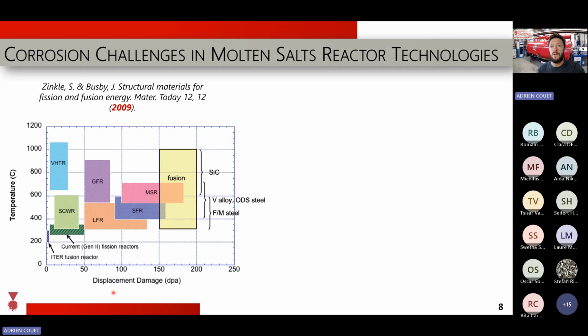So if you look at 1 DPA, which seems relatively low on this scale, 1 DPA means that every single atom in your material has moved on average 1 time from its lattice site, which is a lot when you think about it. If that really happens, then the material just vaporizes and is blasted. There is just nothing left. So thankfully, this is not what's happening in a reactor,